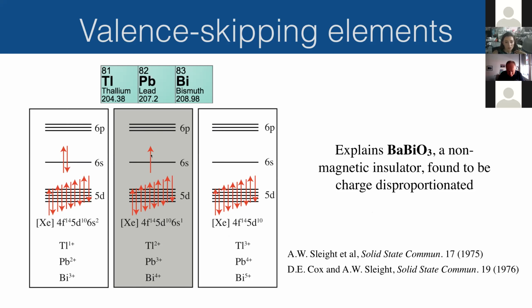So that explains why you don't get barium bismuthate to be a magnetic insulator, a magnetic metal, which you would expect since it's a half-filled spin-half material, nominally. Instead, it is non-magnetic and it is an insulator. And this is because it is charge disproportionated. So you have intercalated sublattices of bismuth 3 plus and bismuth 5 plus. Interestingly, you can dope barium bismuthate and then it becomes a superconductor.